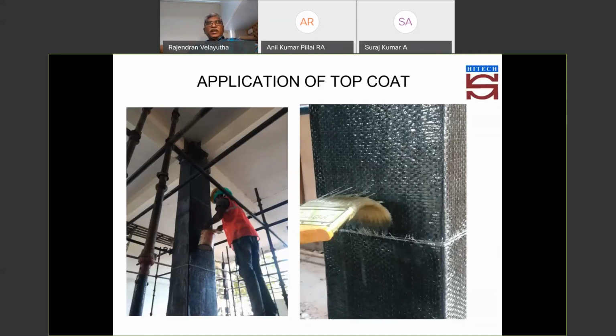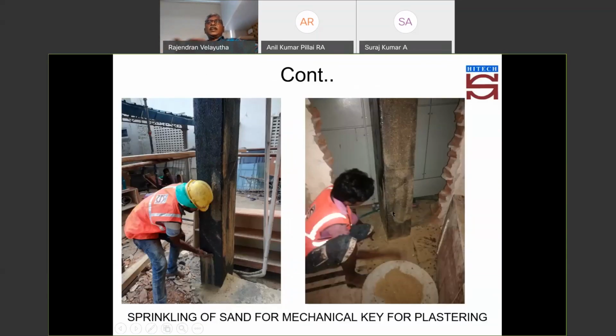As I said, you have one disadvantage of fire. It comes into the picture, and if the structure is outside, UV degradation is likely to take place, because epoxies are not suitable for ultraviolet rays. So what you can do is apply one more layer of adhesive, take sharp sand particles and sprinkle them over the surface so they bond to it. On top of it, you can go for a normal plaster or a gypsum plaster, depending upon the fire retardant property you are looking for.